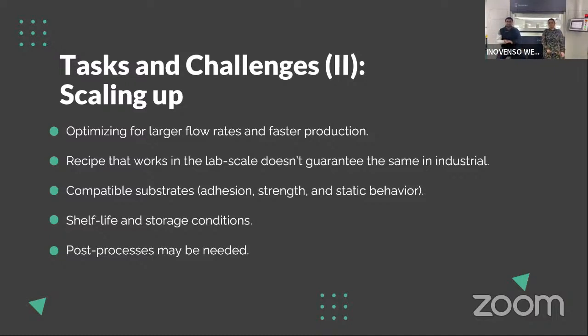Another important thing is, actually this is very important, strength. So let's say cellulose filters, or maybe something derived from cotton, it's biodegradable, but in our past we've noticed that it's not mechanically strong enough for the roll to roll. So when you're setting up a large manufacturing of biodegradable filters, you're going to do roll to roll, as you see in the machine here. If your substrate isn't strong enough, it'll tear off, or even if it doesn't tear off, if it just thins out, you basically compromise the whole production cycle or the roll. So that's something that you want to avoid. So it has to have mechanical strength for your roll to roll tension. Of course, that depends on how much tensile strength it can withstand, and also the type of roll to roll you're using.